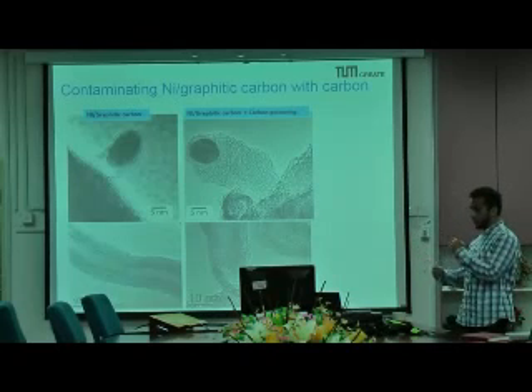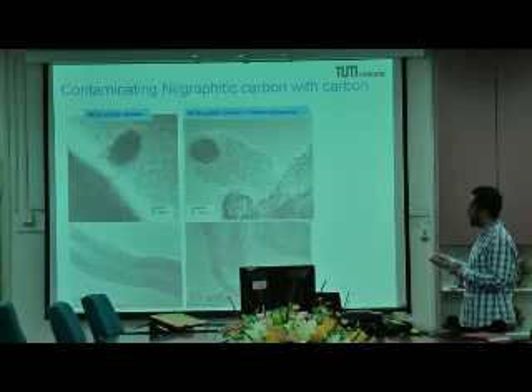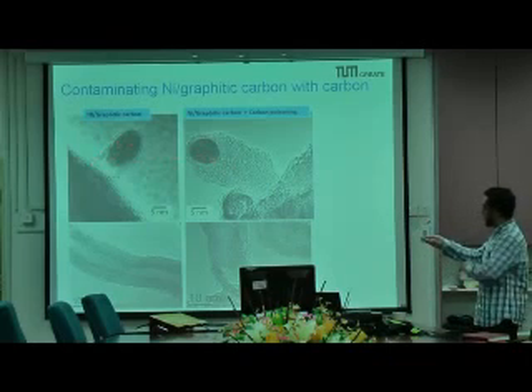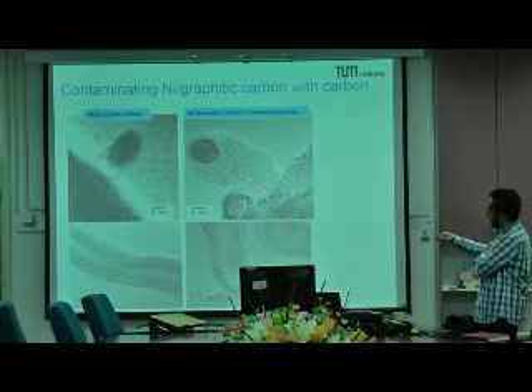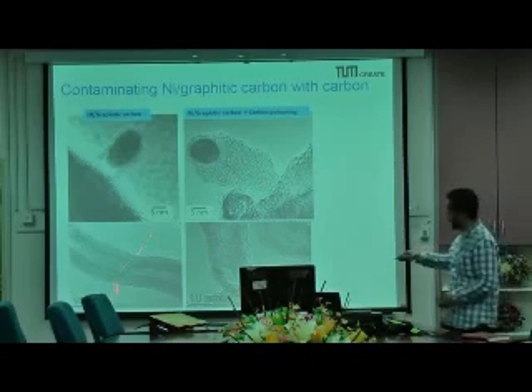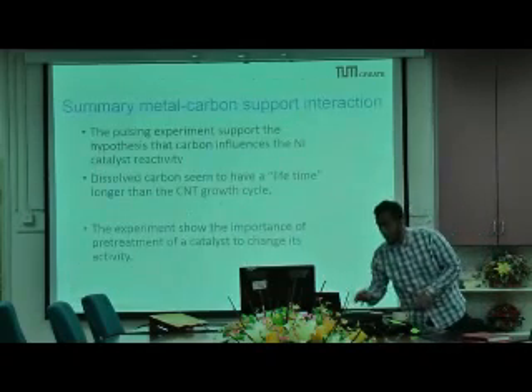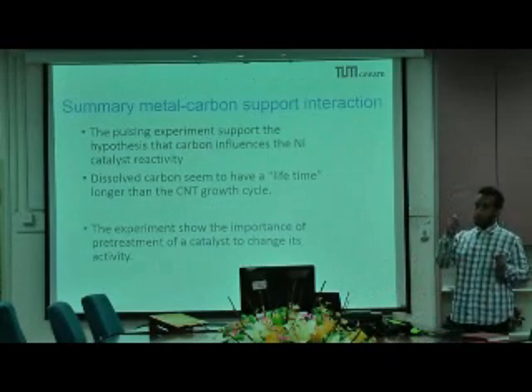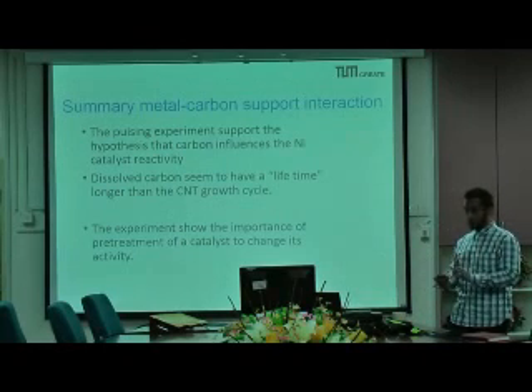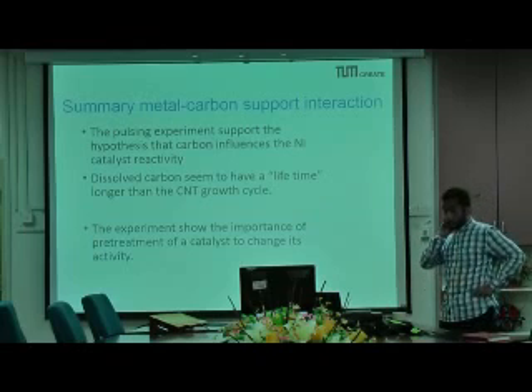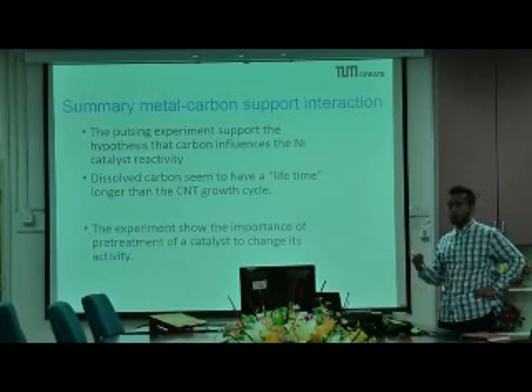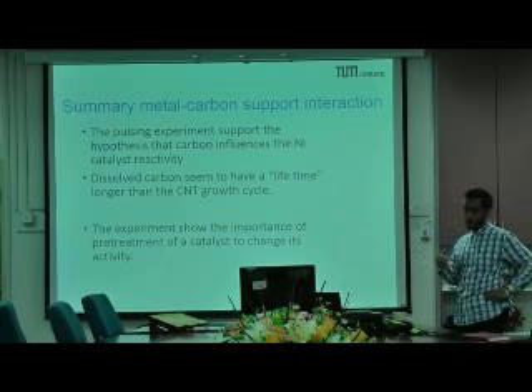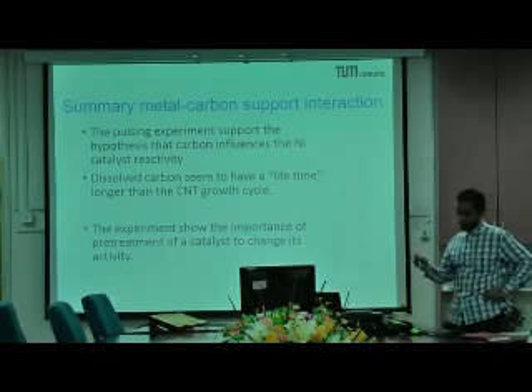So what happened is that if we introduce carbon poisoning after this ethylene reduction, immediately the structure of the graphitic nanotube growing from the catalyst significantly changes. Here you see that the catalyst with carbon poisoning starts to have an irregular plate-like structure, as compared to very perfect long nanotubes on a clean graphitic surface. So that proves our hypothesis that carbon contamination on the catalyst surface or bulk totally changes the behavior of the catalyst. Right, so this brings up an important point: how we choose a carbon material to use as the support and how to pre-treat the catalyst so as not to have some amount of these features.